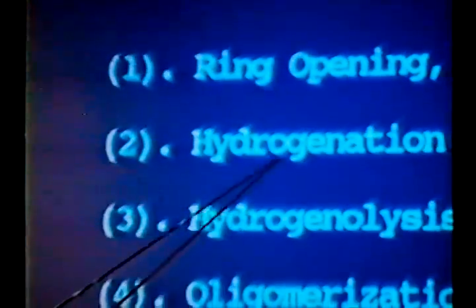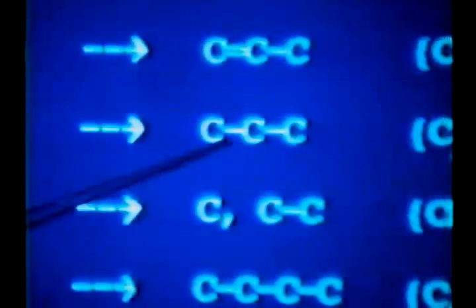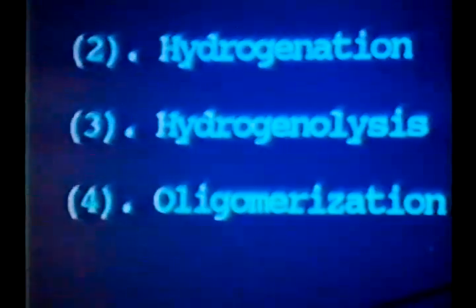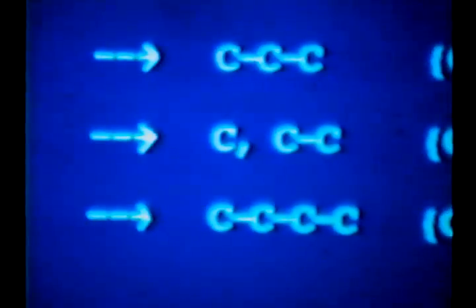What are we doing now? What are the types of reactions we're doing now? Well, we're working with cyclopropane and hydrogen, and we're using a 10-to-1 ratio. The reason for this is that it's a great test reaction. Cyclopropane can ring open or isomerize to form propylene, or it can hydrogenate to form propane, or it can crack to form methane and ethane, or in a strongly acidic system like a hydrogen-type zeolite, it can oligomerize or polymerize to form butanes and higher hydrocarbons.